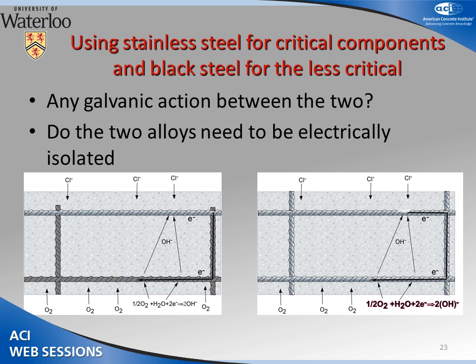The concern, though, was the interaction between the stainless steel and the black steel. Is there any galvanic interaction between them? So, for example, if you have stainless steel at the top and black at the bottom, and the chlorides should go all the way down to here, would the fact that the black steel is connected to the stainless steel provide a greater corrosion rate for the black steel than it would do if it connected to black steel? In fact, it's the absolute opposite.